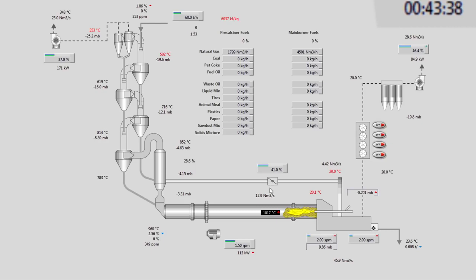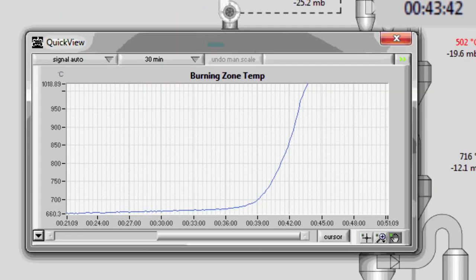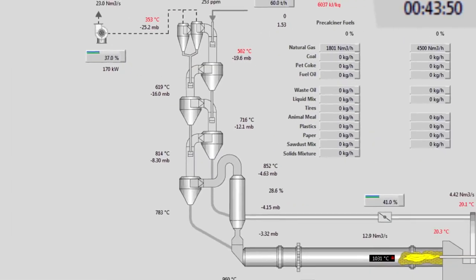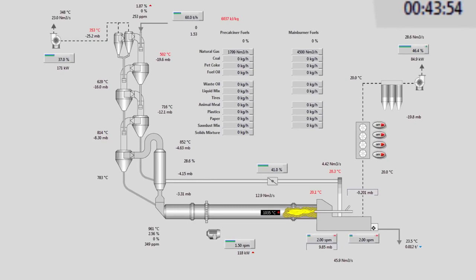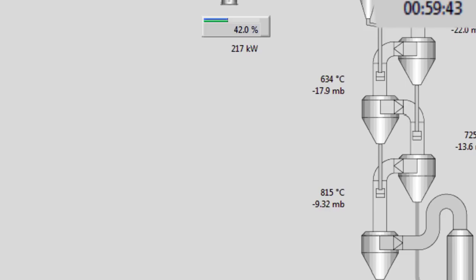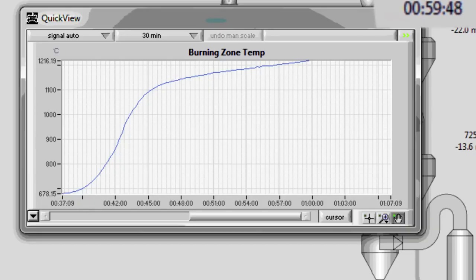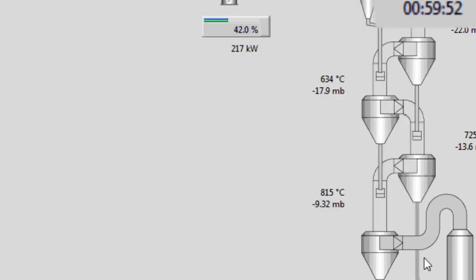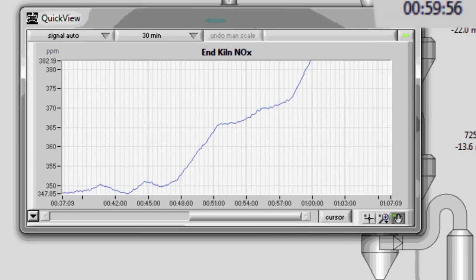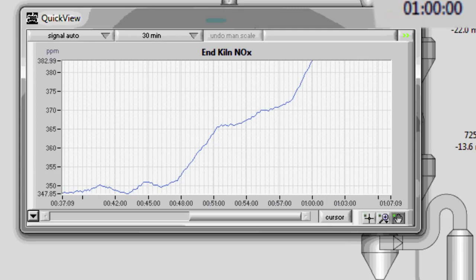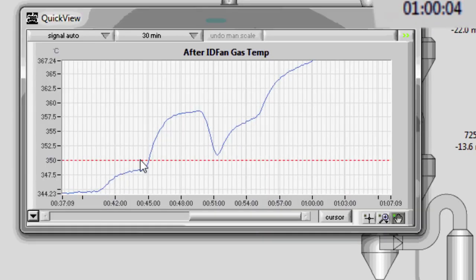Minute 43, BZ temperature shows a sudden increase, material is there. One hour, BZ temperature increasing steadily. Kiln NOx as well. Temperature at ID fan is way too hot. Notice that at minute 50 I already increased 4 tons of feed. It helped to cool down the gases, but now I must act again.